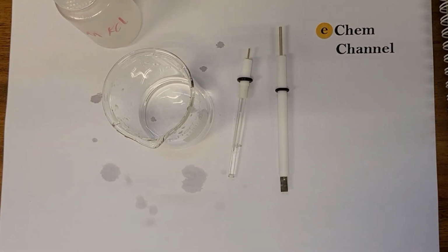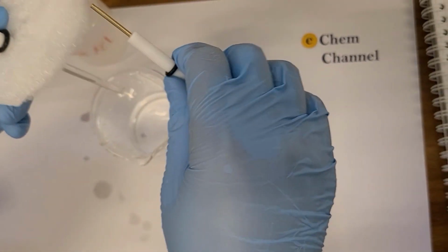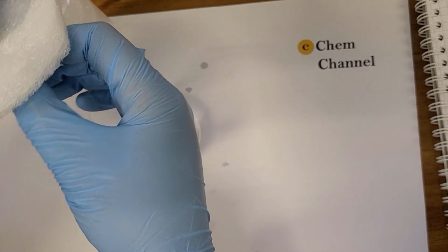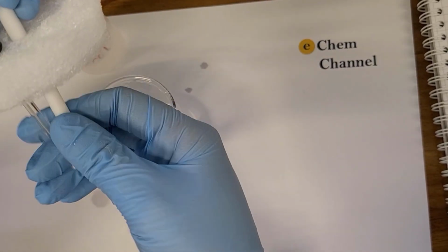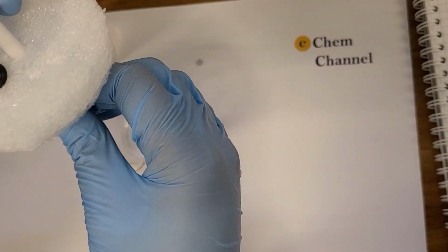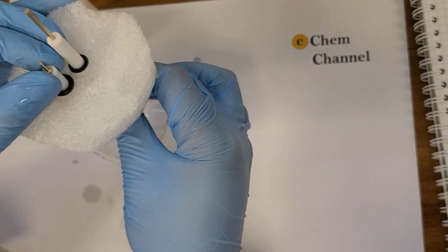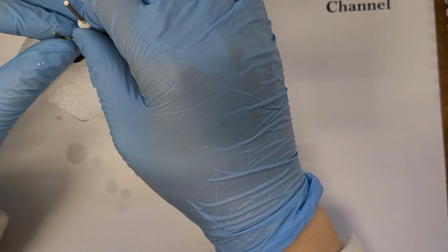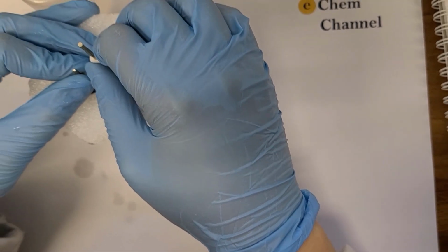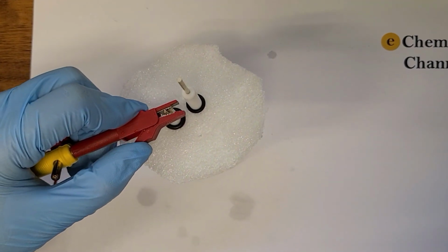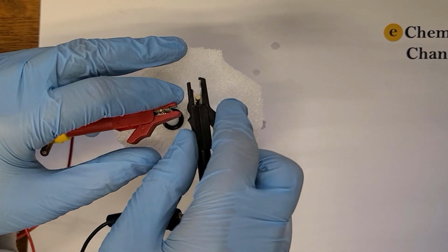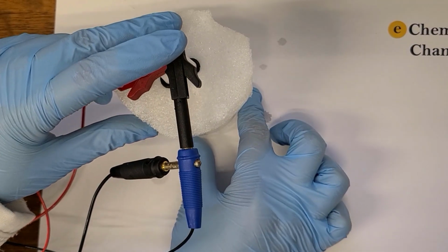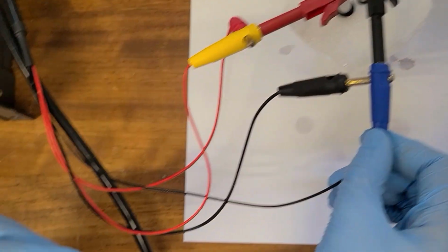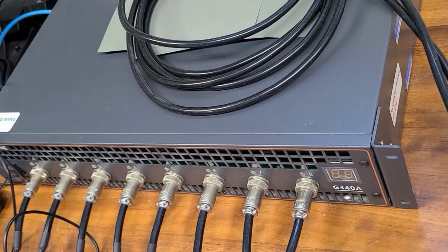So we prepare a beaker and insert the reference electrode into a foam together. We pair it with a platinum electrode. And we put both electrodes into the 3.5 molar potassium chloride electrolyte. Then we connect the positive electrode with the reference electrode and the negative electrode with the platinum electrode. And then we apply a small current overnight in order to get the silver chloride coating.